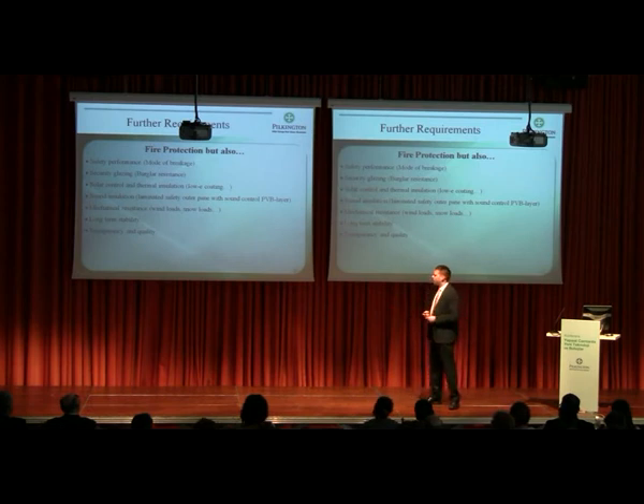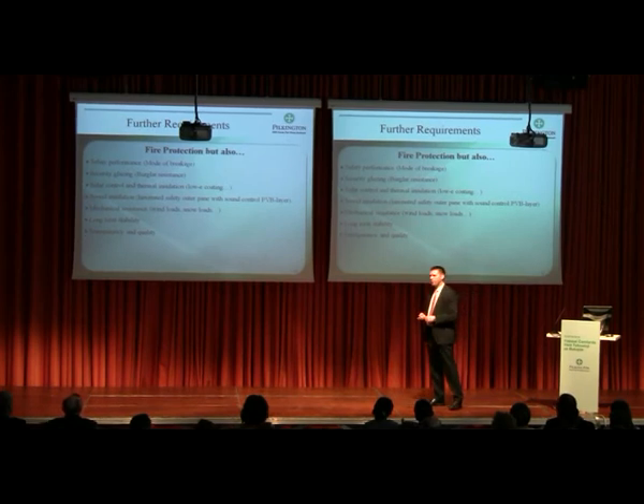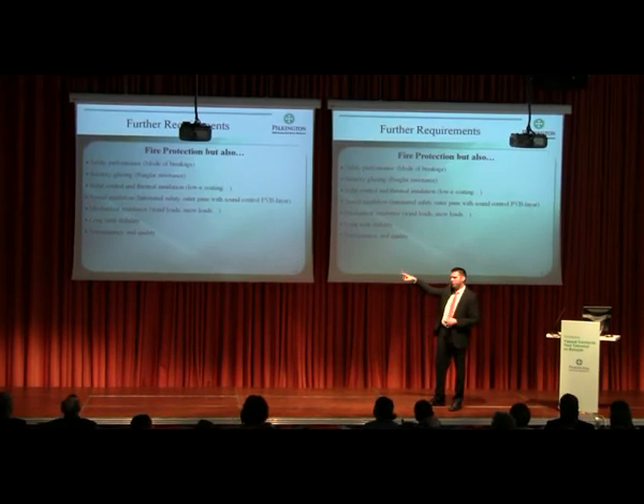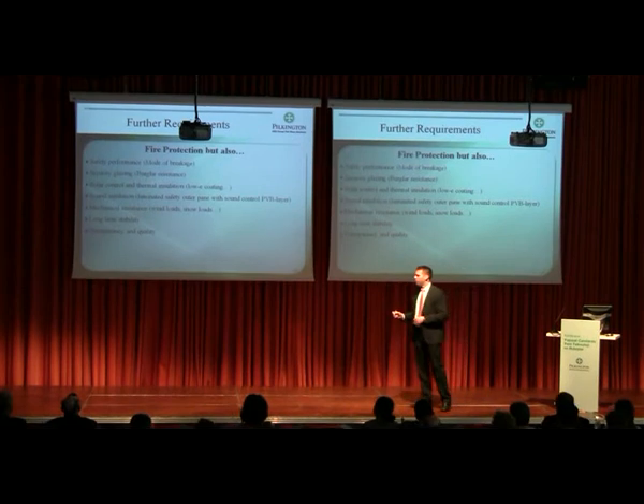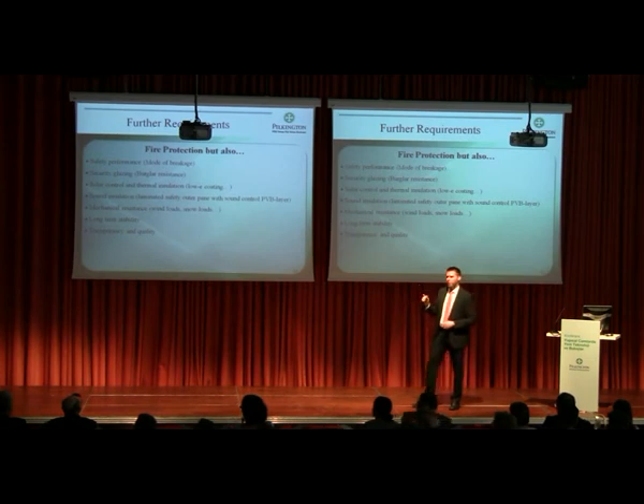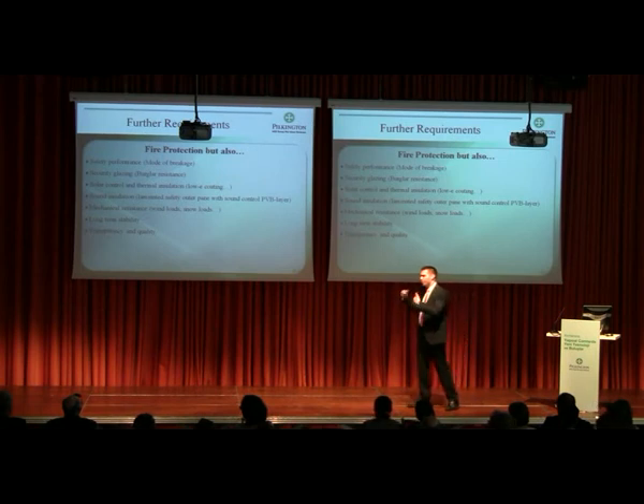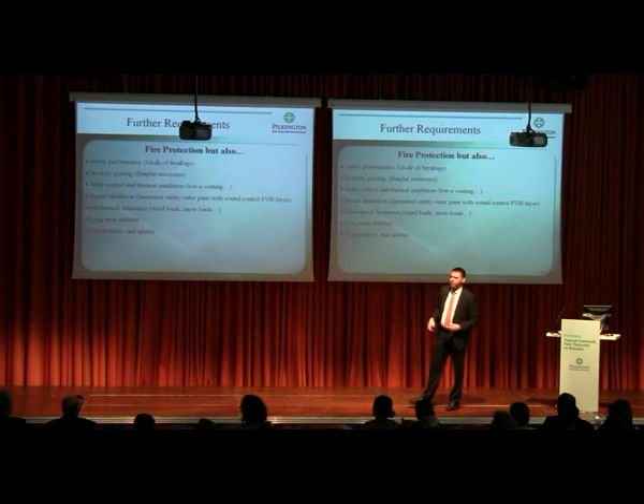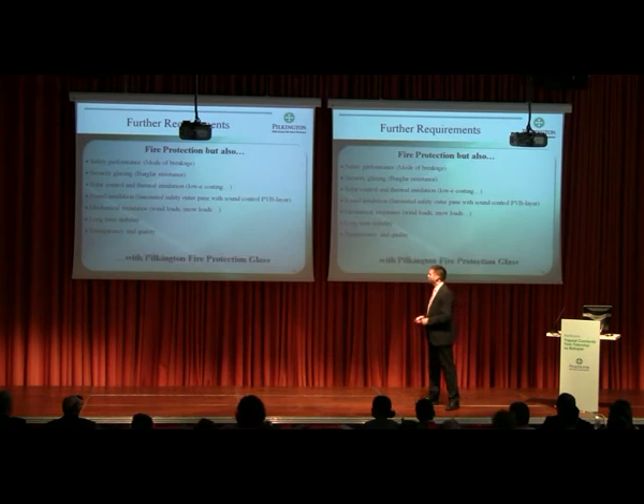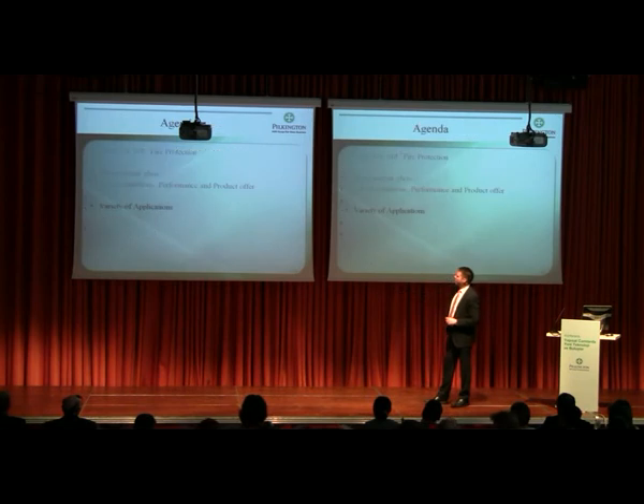Transparency and quality. I would say that you won't really see if a fire protection glass is installed or not due to the high transparency we can see. So you can have a look at the glazed door. I guess it's 90 minutes type, so it's 37mm thick. You can see if you see any difference compared to a normal 6mm or 8mm glass regarding the appearance and the light transmittance. So just go around after my presentation and have a look at the door to see what is possible. Okay, all those requirements are possible with fire protection glass.